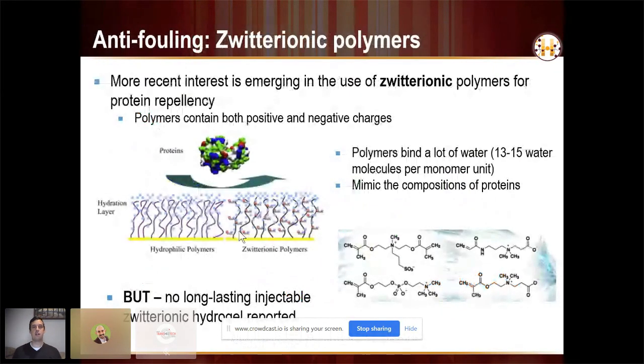The other polymer that's attracted a lot of interest recently is zwitterionic polymers for antifouling. A zwitterionic polymer is a polymer that has a negative and a positive charge in the same monomer repeat unit, and these are typically very close together. You can see the monomer structures on the bottom right there. Typically, this is a quaternary ammonium group, which is a positive charge, and then two to three carbons away, there's a negative charge, which could be from a sulfate group, a carboxyl group, or a phosphate group most typically.